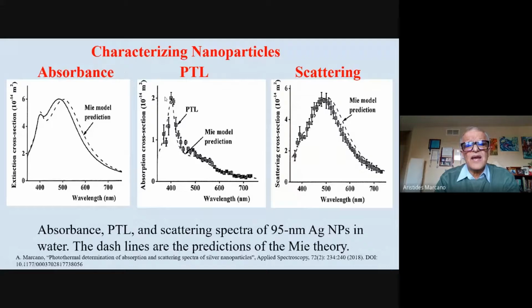But the interesting thing is when you do photothermal lensing, the prediction of the Mie theory for the photothermal lensing is very different. It has some peaks. These peaks are the plasmonic peaks of the nanoparticles. And there is another, secondary plasmonic peak that is also predicted by the other people right here, around 500, and around 400 you have one plasmonic peak. But that is also predicted by the Mie theory. What happens is that our measurement in photothermal lensing has a very good coincidence with that Mie theory, which is absolutely different from the absorbance, as you can see.